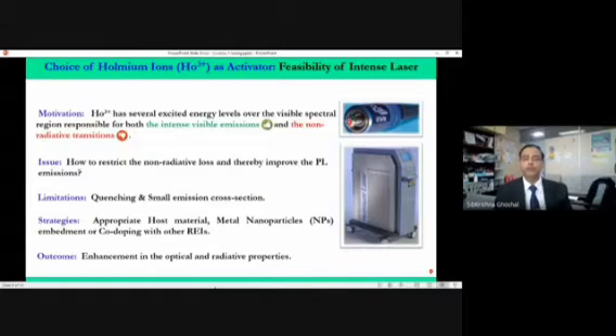We can put a lot of different kinds of metallic nanoparticles, but among them, silver and gold are the best. Silver has the surface plasmon resonance. So when we put this kind of nanoparticle inside the glass ceramic and then bring the rare earth in front of them, an interesting thing happens. A plasmon-mediated effect happens. This plasmon-mediated effect can push the absorption and emission cross section of the rare earth very high.